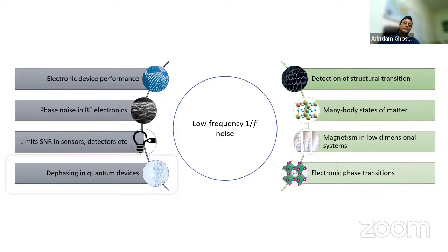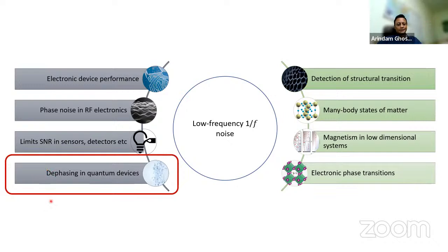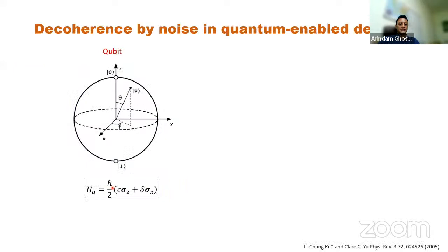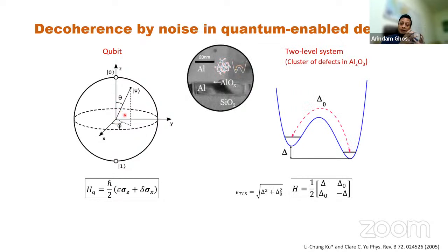Okay. So I'm going to give you a very quick example of why this talk is trying to motivate people about why noise is an important quantity to me. Let me tell you a little bit about dephasing in quantum devices. A quantum device is based on, say, for example, you want to make a qubit for a quantum computer, and that qubit exists in two states, 0 and 1. And this is a typical Hamiltonian of this. When you try to make a real qubit, one of the most important workhorses is aluminium oxide, aluminium Josephson junctions. And this aluminium oxide, which is an amorphous oxide grown as a tunnel barrier between two aluminium superconducting channels, can contain defects. Those defects contain two level systems. Those are usually clusters of atoms, there are varied possibilities.